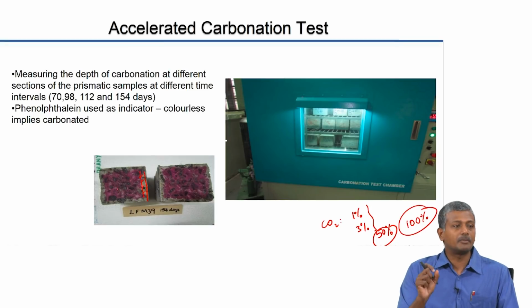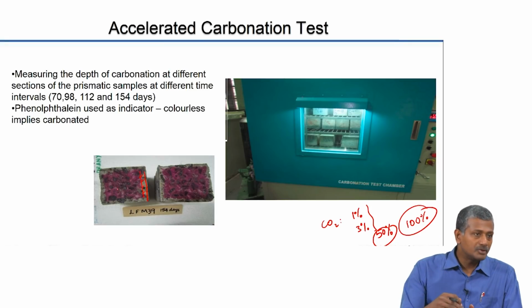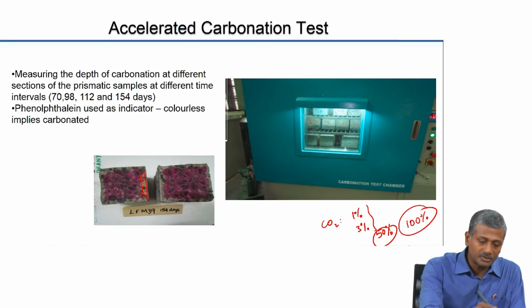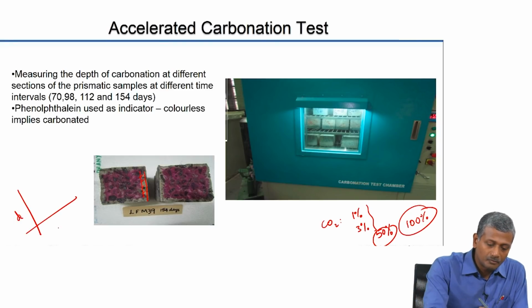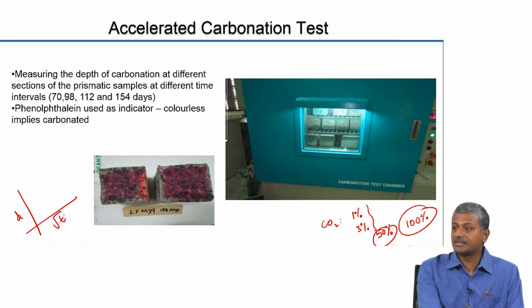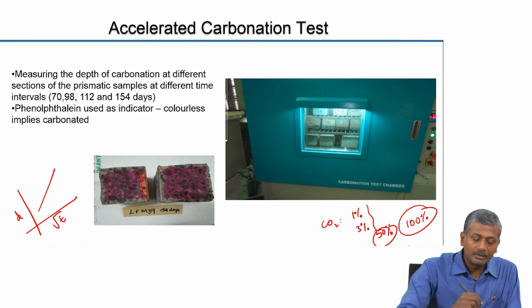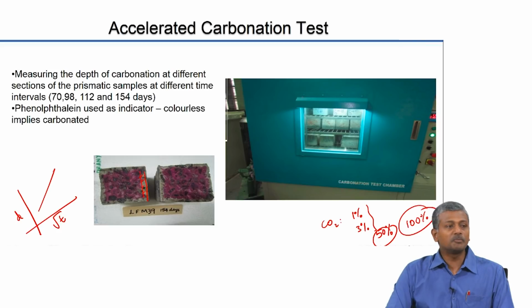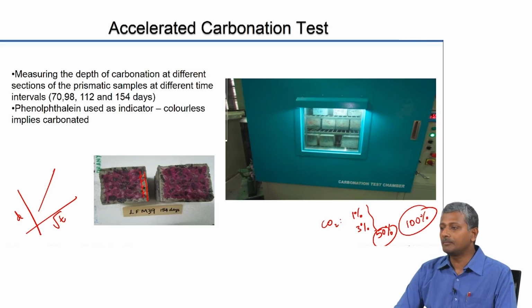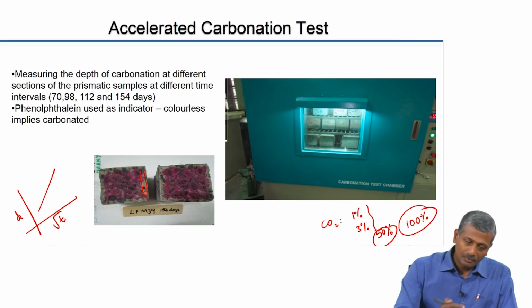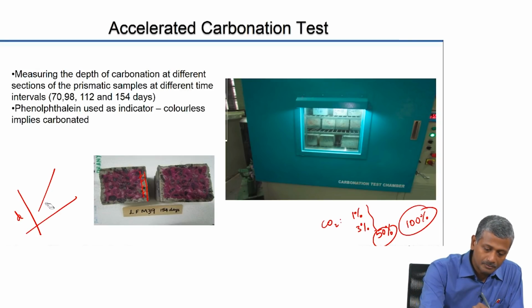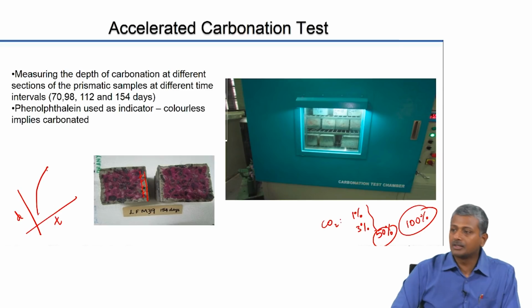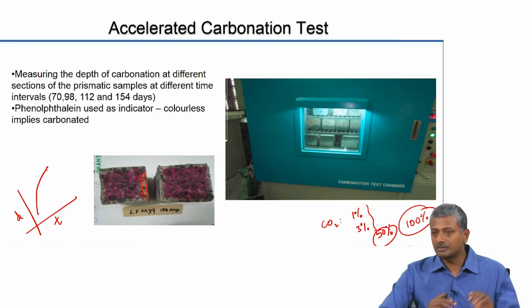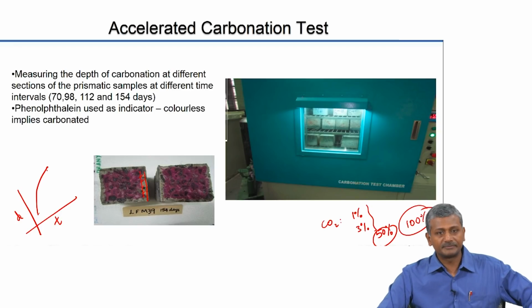You can measure the depth of carbonation, and then with respect to time, when you plot this depth, what you generally obtain, I will show you some data later, when you plot this against square root of time, you get a linear relationship. The depth of penetration of CO2 plotted against the square root of time gives you a linear relationship. What does that mean? If you plot against time, what will happen? You will get a quadratic relationship, which sort of starts tapering off towards the end. That is why when you plot it against square root of time, you get a linear relationship.